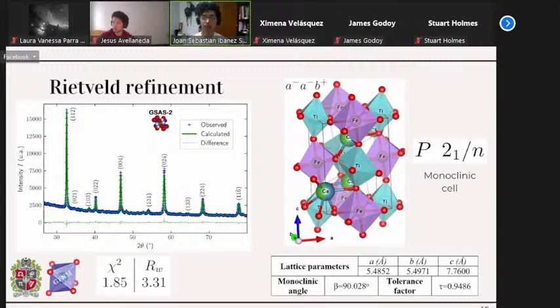the different inclinations that it has. And we can see, or we found that the Glazer notation for the inclinations is actually a-a-b+. That is, we have two tilts, or if you see through the A direction or the B direction, you are going to see octahedra out of phase. And if you see along the C-axis, you are going to see octahedra in phase. That would be this part.